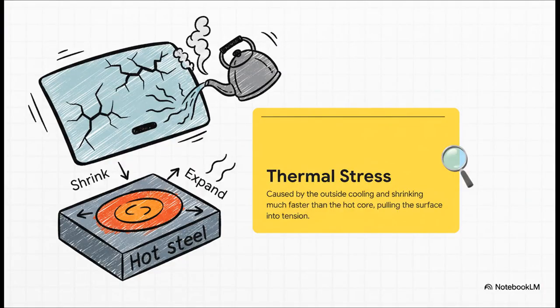Okay, so the first combatant in this war is something called thermal stress. The best way to think about it is to imagine pouring boiling water onto a frozen car windshield. That sudden, uneven temperature change can make it crack, right? Well, the exact same thing is happening here. The outside surface of the steel cools and shrinks almost instantly, while the core is still blazing hot and expanded. This huge mismatch pulls the surface into some really extreme tension.